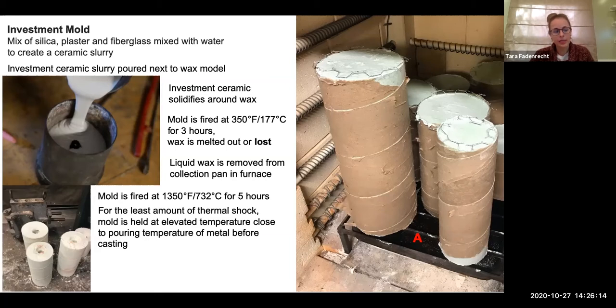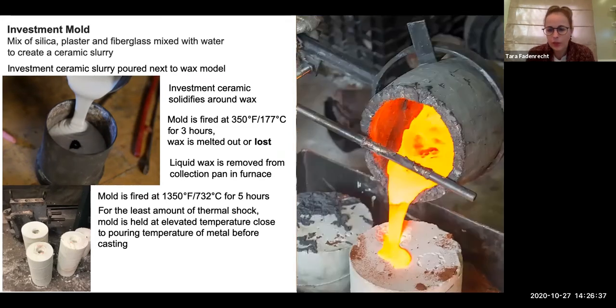If there's less shock to the metal as it comes into contact with something cold, it tends to want to freeze and seize on you. You can alleviate that by keeping the metal hot, and you're more likely to get into those thinner areas due to less of a temperature gap between the ceramic material and the metal. Then you would heat up your silicon bronze. You want to pour that into the molds. The molds are allowed to solidify, again, depending on the size. For what we're looking at, it's about 20 minutes. You want to just let the metal completely solidify before you break it open.